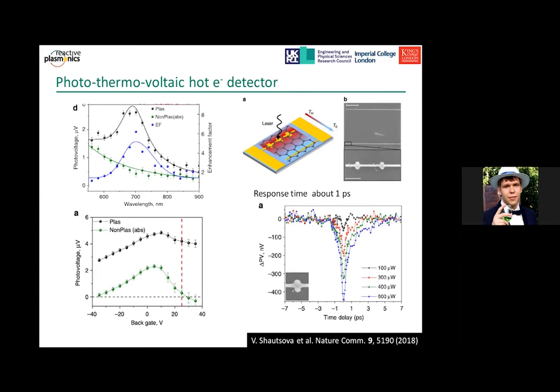This additional contribution was identified as being produced by hot electron diffusion within the graphene channel. The hot electrons produced by the plasmon excitation diffuse inside the graphene channel, and therefore produce a photothermal voltaic effect depending on the gradient of the electronic temperature.